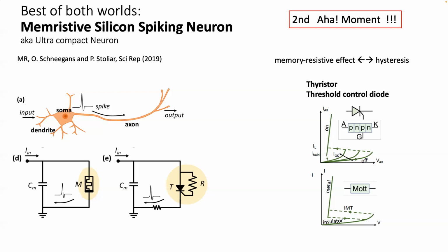When you combine the thyristor with one resistor between two of its three legs, it becomes a memristor that can switch between high resistance and low resistance with hysteresis. So this is the integrate-and-fire model, where you have a current that is integrated by a capacitor. Initially, the memristor is open, so there is no current through it. All the current charges the capacitor. The charge raises the potential in the capacitor, and when the potential reaches the threshold of this memristor, the switch goes down. The system is conductive, and this capacitor discharges very fast, with a very fast time constant, through the memristor. Crucially, the memristor remains closed until the capacitor empties its charge and the current goes down.